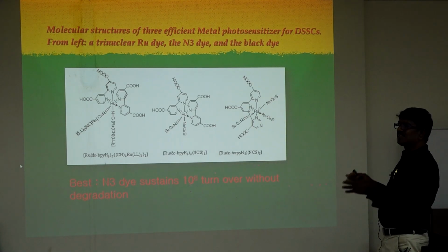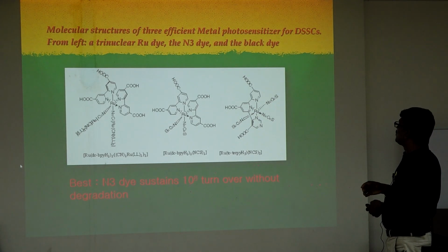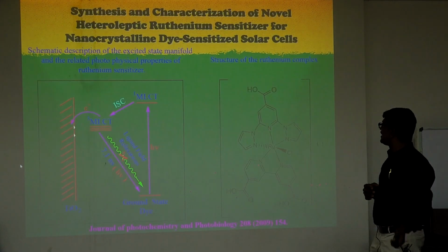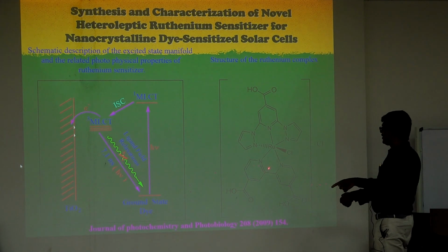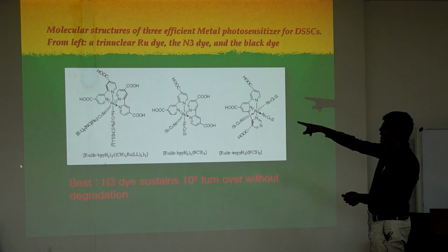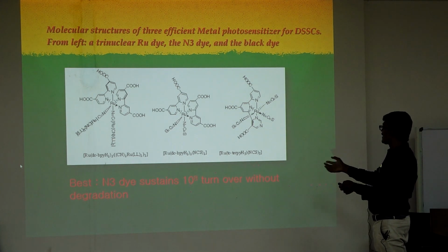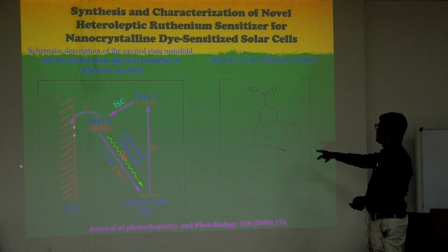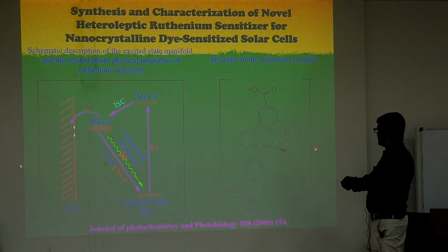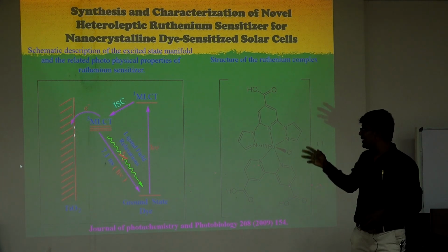Seeing the structure etc., in general we want to modify it in our lab. So we want to do some modification of a dye-sensitized cell in our laboratory conditions. What we do is take a bipyridine. You noticed here they use either bipyridine or only terpyridine, but we take one bipyridine and one terpyridine, and then chlorine or thiocyanate or CN. We change this functional group here, chlorine, thiocyanate, CN, and we prepare different dye molecules in the laboratory.